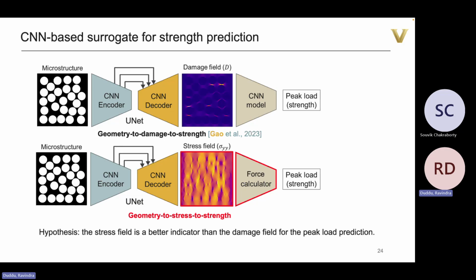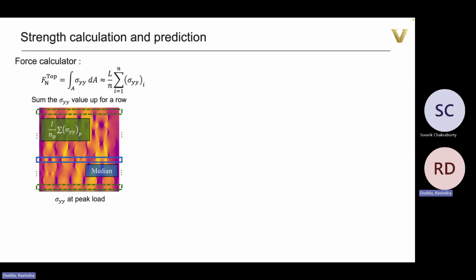we did this whole research. Our paper got accepted, and then we were thinking and said, why did we do it that way? We should have done it this way in the first place. And so sometimes that does happen, right? That you get these ideas a little bit too late than when you should. But then we said, okay, let's do the stress field and then just integrate it along the line, and then you get the peak load. And the hypothesis is that stress field will give a better indicator for the peak load than the damage field.